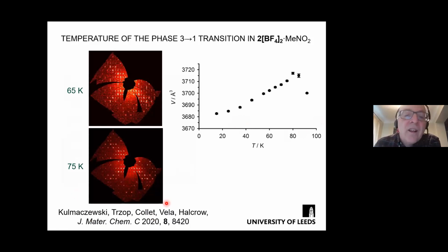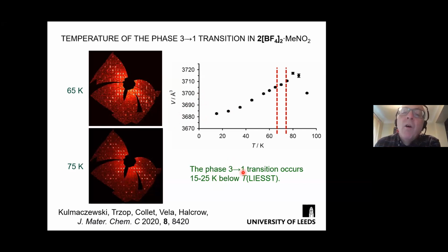Well, the next thing we did was we measured the temperatures of these phase changes more accurately. In the high spin state, after irradiation, so this is the photo-excited crystal, the phase 3 to phase 1 transition occurs at this temperature. You can see in this part of the diffraction image, for example, some diffraction spots have gone between here and here. So this is the phase transition temperature, and it's about 20 Kelvin below the spin state relaxation.